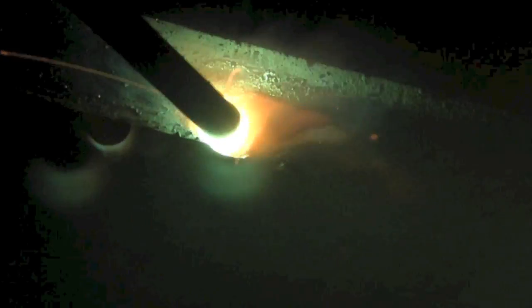And their amperage range on the box said 120 to 170, I think. So I was up around, you can hear the machine groaning. So maybe some issues going on there too. I'll talk about that in a minute. I'm running the second pass here with the same 7024 1/8 rod at around 200 amps alternating current. And something's just not quite right. Just not flowing like a 7024 should.